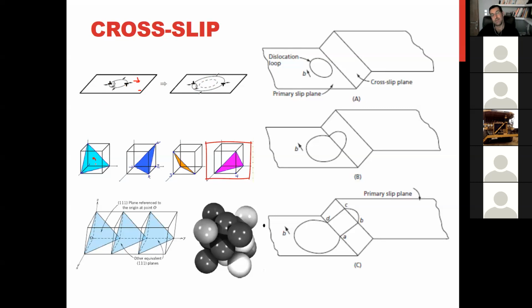But you will see we have 4 similar planes inside of the FCC that make angle. For example, this plane that we are talking about has angle with this plane, like this. It means this is another plane, equivalent plane inside of the crystal, yeah? So this dislocation, if it can move inside of the plane, if it's coming here, why it cannot cross slip to another plane? This also can happen, yeah? So this dislocation can change the slip plane from this plane to this plane. That we call it cross slip, yeah?